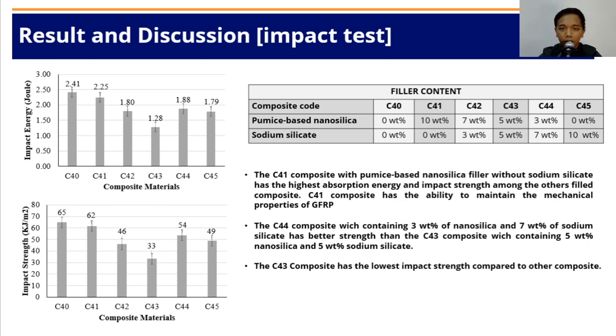From the following chart, it can be seen that C44 composite, containing 3% nanosilica and 7% sodium silicate, has better strength than C43 composite, which contains 5% nanosilica and 5% sodium silicate. This phenomenon is due to the role of sodium silicate in the distribution of homogeneous particles, which can help to minimize porosity. The C43 composite has the lowest impact strength compared to the other composites.